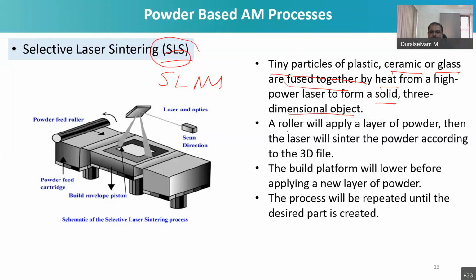And after doing that, a roller will apply a layer of powder. Then the laser will sinter the powder according to the 3D file, and the build platform will lower before applying a new layer of powder. So basically, again, it is a layer by layer deposition of the powder particle. Sintering happens, lower the powder bed by one layer thickness, then again apply the powder, lower the layer by one layer thickness, likewise it goes.